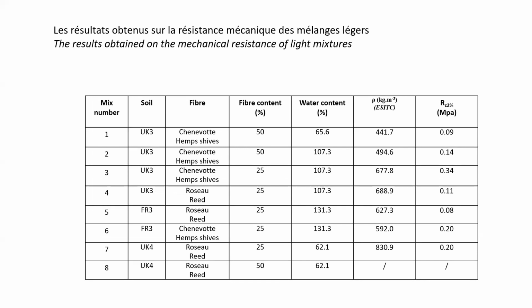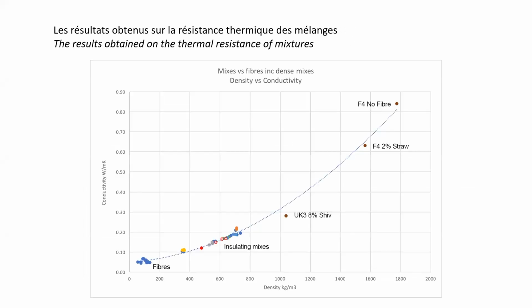So these different samples of light earth were then tested in terms of compressive strength to see their capacity at load bearing themselves, to see if they could take some load, some weight, and we tested these especially on the thermal insulation side of things. So here you can see the results on this graph. You've got the different samples, mostly at the bottom left here, where you've got insulating mixes. Here you can see all the different samples that we tried out. You've got a thermal conductivity that goes between 0.1 and 0.2, depending on the density variation. So this curve shows us the relationship that exists between thermal conductivity and density. These have already been studied in the past, so it wasn't anything groundbreaking here.